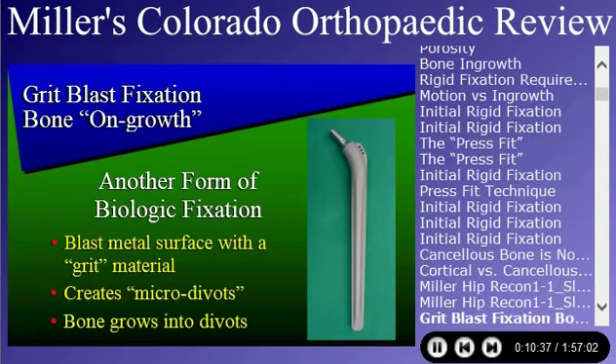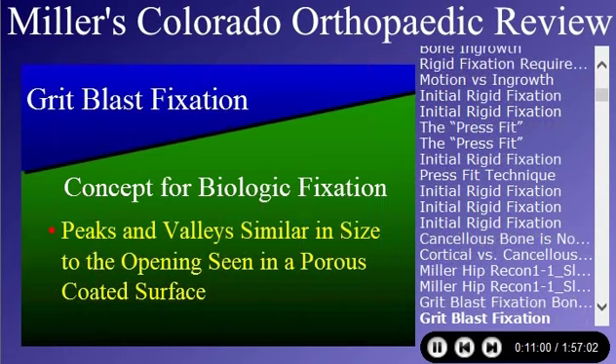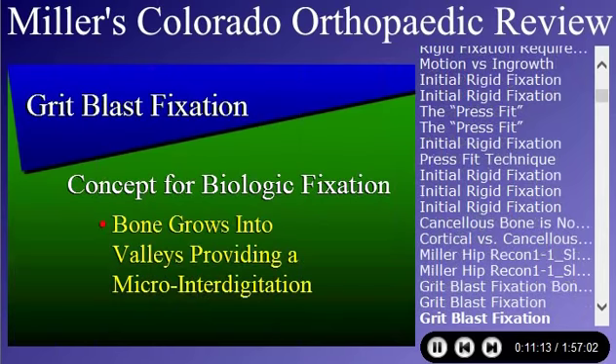Now, there's another form of biologic fixation. That's what we call grit blast fixation. It's basically a way of what we call bone on-growth. What you're doing with a grit blast stem is you're blasting it with some particles, either hydroxyapatite beads or glass beads, and you create literally micro divots in the metal, and the bone grows onto these divots. And if you do it right, the peaks and valleys that are these divots are similar to the openings seen in porous-coated surfaces. So you've got to pick the beads of the right size. You hit the metal, and you get these little valleys that are similar to the pores, which you would normally see for a porous-coated surface. And the bone grows into these valleys, providing a micro-interdigitation.